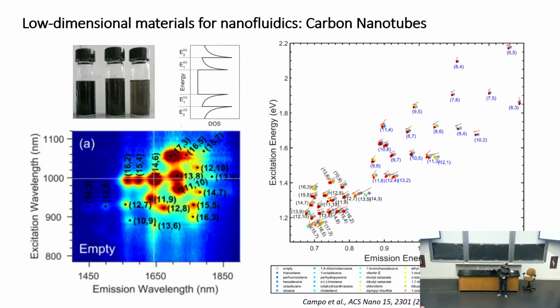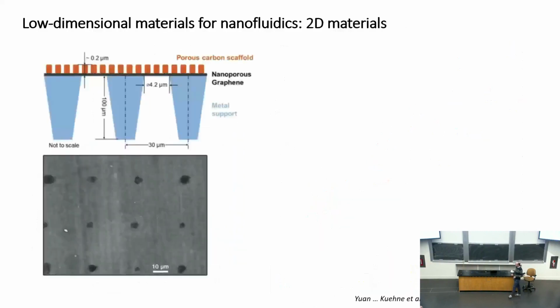So now we know these are plots you see in the field over and over again, where people can vary emission wavelengths and excitation wavelengths and get emissions at very different energies for these different CNTs. So you see like (13,6), (12,8), (11,9). And I'm showing this plot just because it's busy, actually. You see there's all these CNTs, and people actually do achieve filling with all these different molecules, including water, which is down here. So we know from experiment that we can actually do this, and so this makes this a very useful platform.